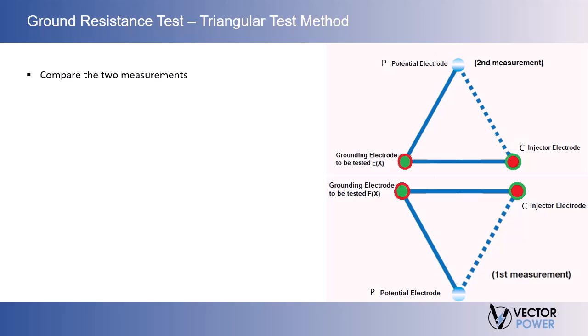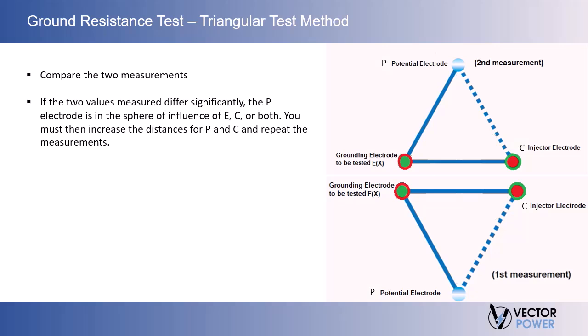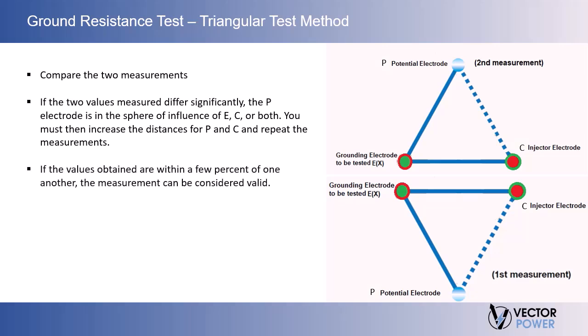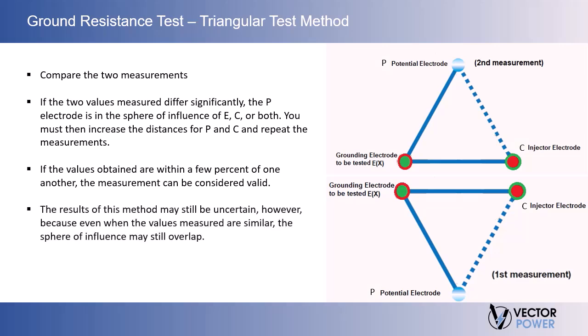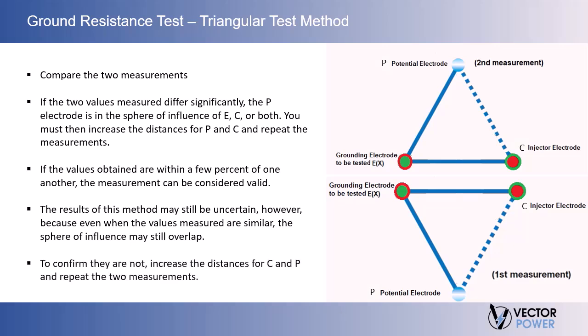Compare the two measurements. If the two values measured differ significantly, the P electrode is in the sphere of influence of E, C, or both. You must then increase the distance for P and C and repeat the measurements. If the values obtained are within a few percent of one another, the measurement can be considered valid. The results of this method may still be uncertain, however, because even when the values measured are similar, the sphere of influence may still overlap. To confirm they are not, increase the distance for C and P and repeat the two measurements.